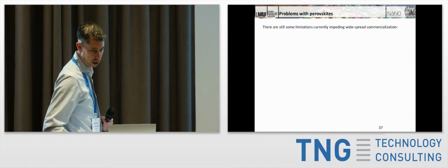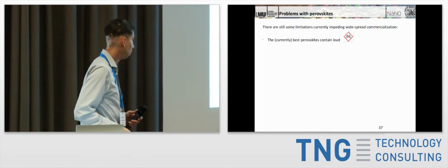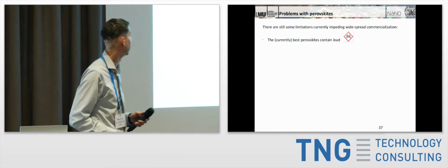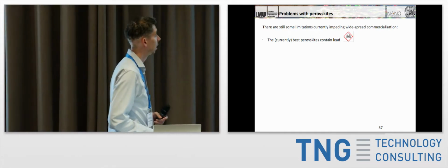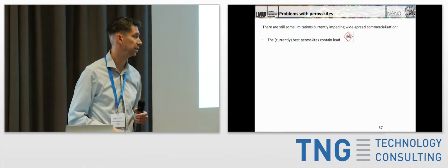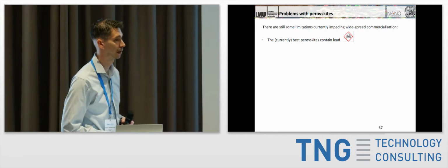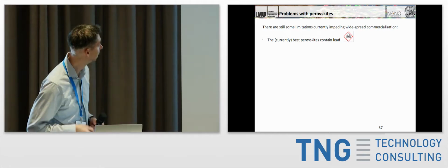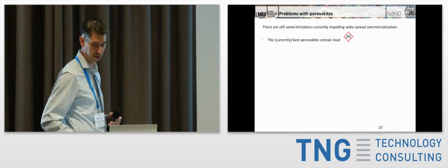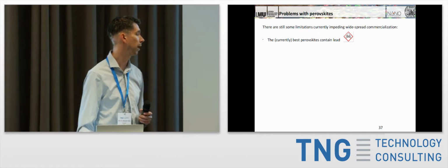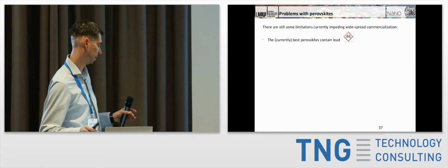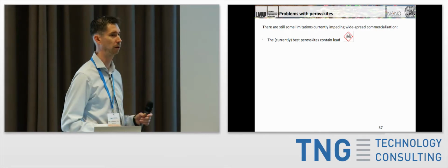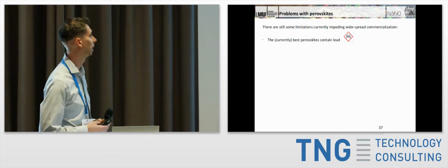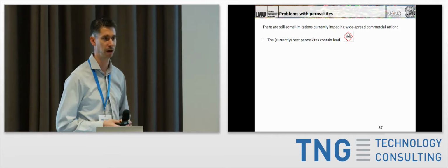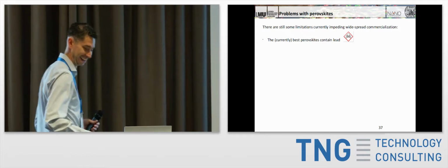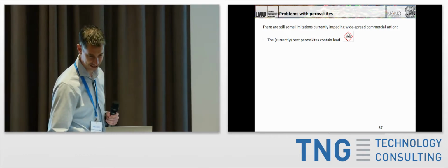Okay. So there are still a couple of limitations. Perovskite's not all perfect. There are a lot of things that currently impede widespread commercialization. One of the big problems, especially in Europe, is that it contains lead. At least most of the efficient perovskites contain lead, and the European Union does not like lead at all. So that's one of the big problems for putting it into TVs or solar cells. Although if you covered the entire land mass with perovskite solar cells and had them leak out completely into the ground, you wouldn't be able to detect any of the lead behind the background contamination that you have of lead anyway. Nevertheless, the European Union doesn't like lead.